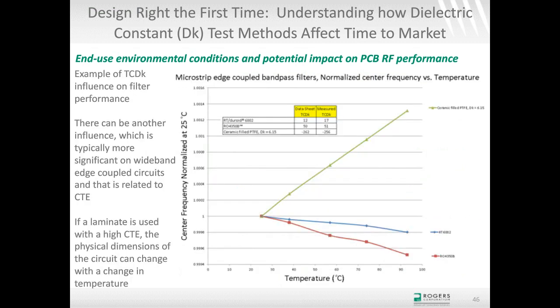Last slide, TCDK, temperature coefficient of dielectric constant. And this is showing some real-life measurements I did on filters. These are microstrip edge-coupled bandpass filters, and I'm showing center frequency differences, normalized at room temperature and normalized to the center frequency. What you can see is the materials with the higher TCDK, that's the green curve, are definitely much more affected by the change in temperature, which is on the x-axis, going from about 0 degrees up to, it looks like, about 90 degrees C.